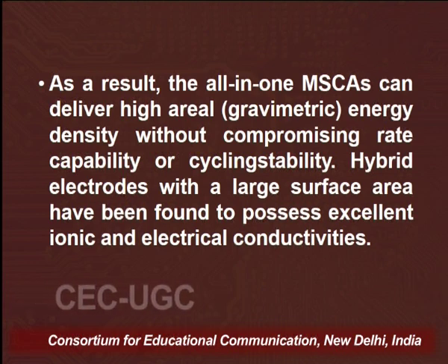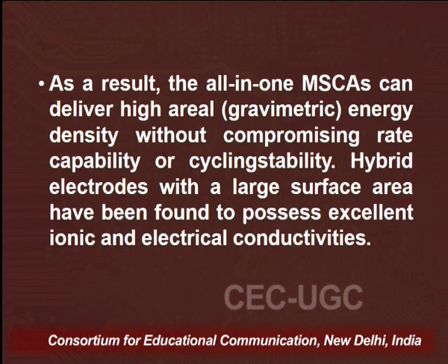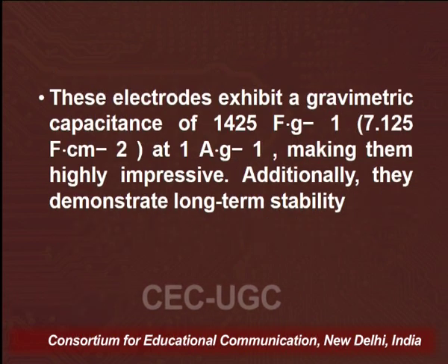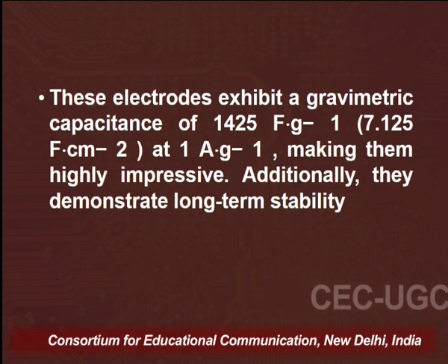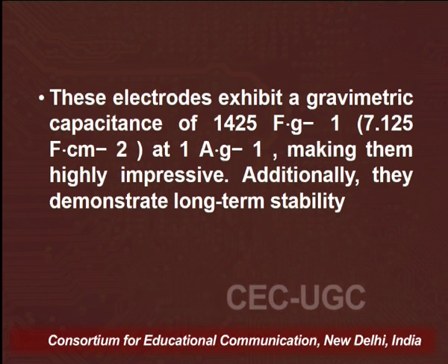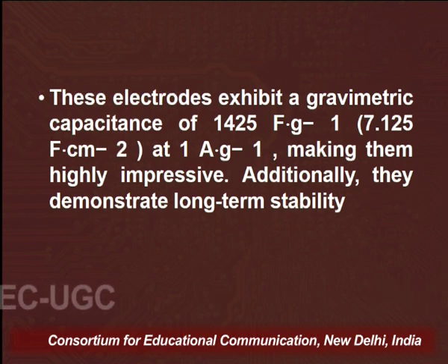The hybrid electrode with a large surface area has been found to possess excellent ionic and electrical conductivity. These electrodes exhibit a gravimetric capacitance of 1425 F g^-1, that is 7.12 F cm^-2, making them highly impressive. Additionally, they demonstrate long-term stability.